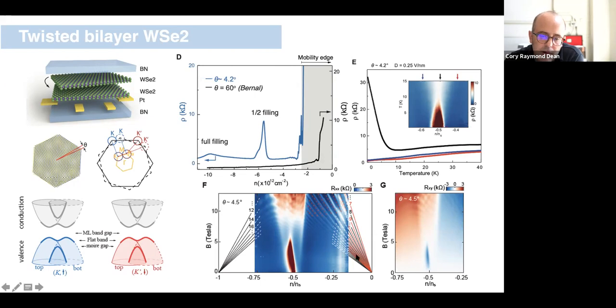So in this figure, projecting to zero field allows us to identify on the right where the intrinsic top of the valence band is, the intrinsic band edge of the WSe2 is. And then on the other side, we see these fans allowing us to project to where full filling is. That allows us to identify in density units that this peak is actually a full filling peak. And here, where we can identify where the zero filling band edge is. So we can make the conversion, therefore, from density to filling. We can identify that this peak here really is at half filling.